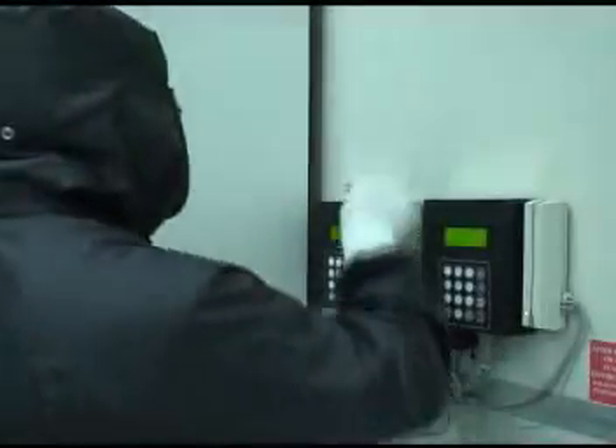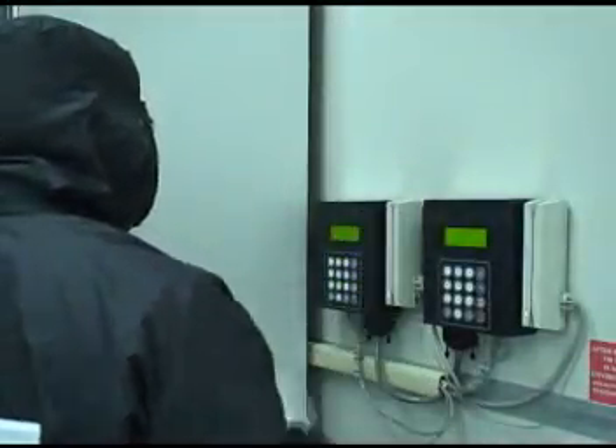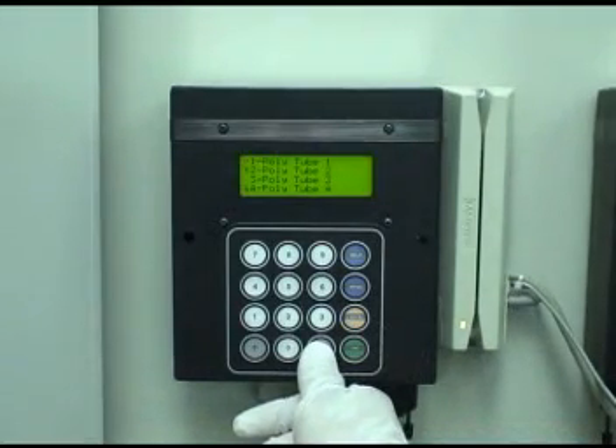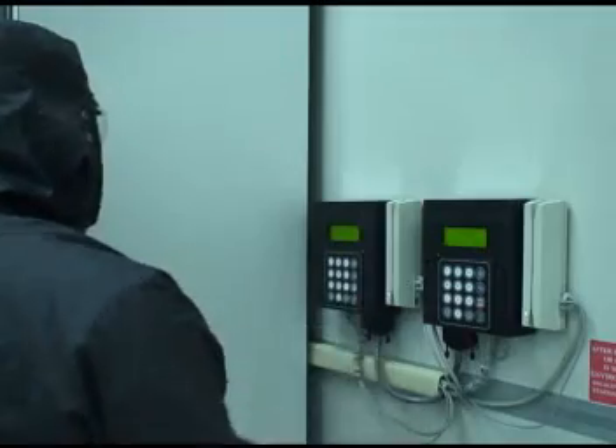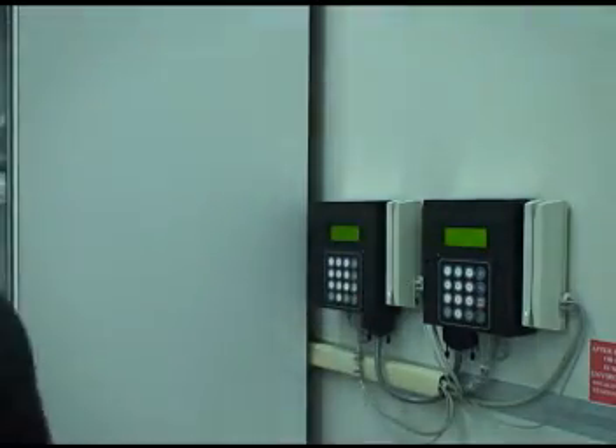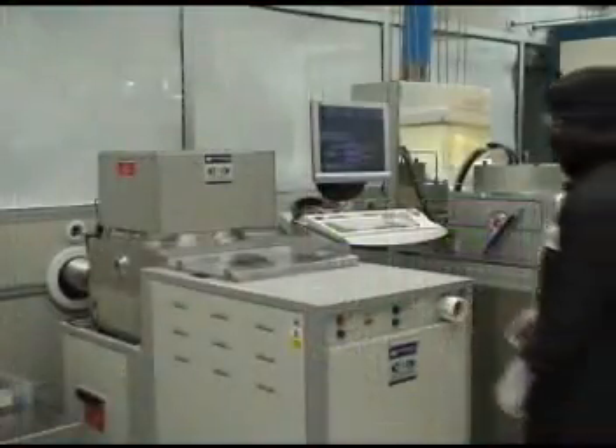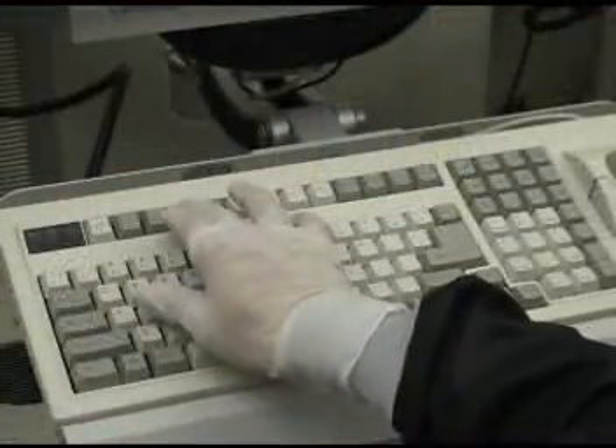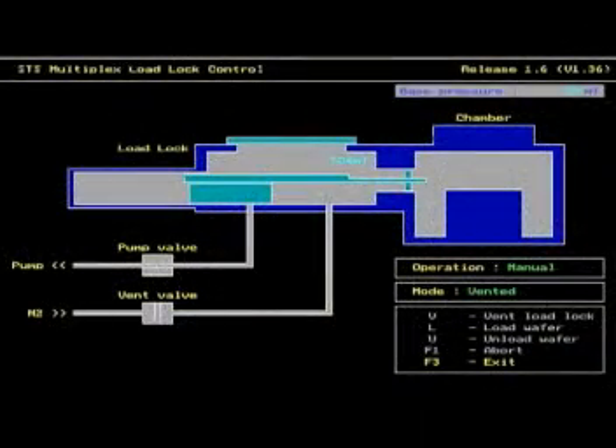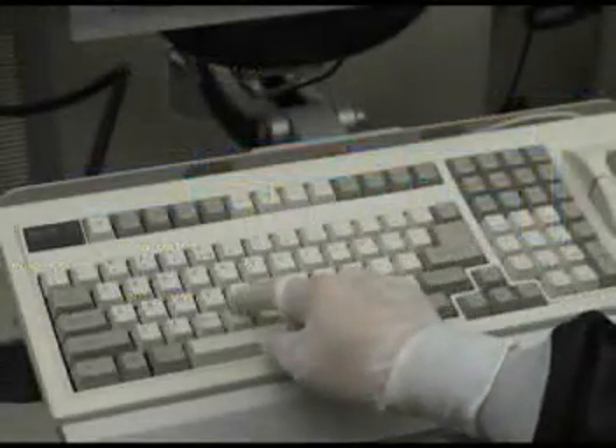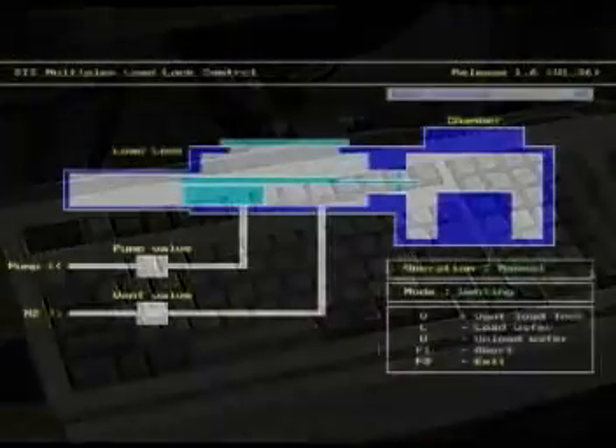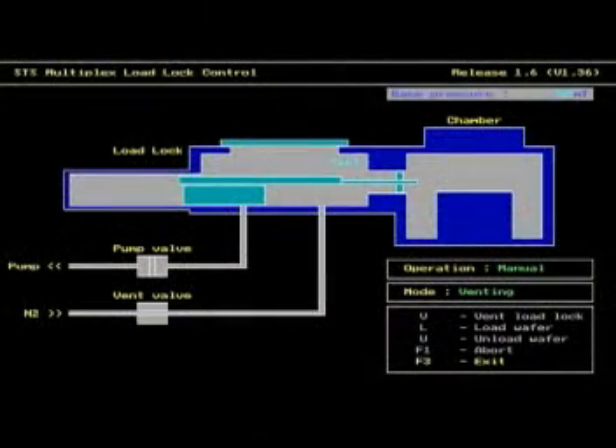Before you can begin using the STS PECVD, you must first log into the system at the access controller. Once you have done this, you can begin loading your sample. To begin, you must press the F3 button in order to select the load-unload screen. Then press the V button in order to vent the load lock. The system will cycle through the vent process 4 times, which will take a few minutes. You will know that the system has reached atmosphere when the load lock pressure reads 760 torr.